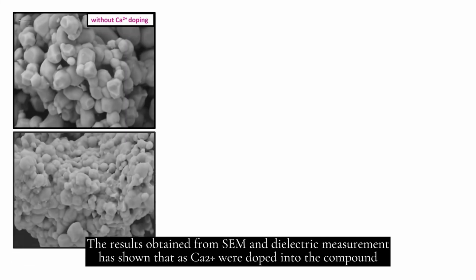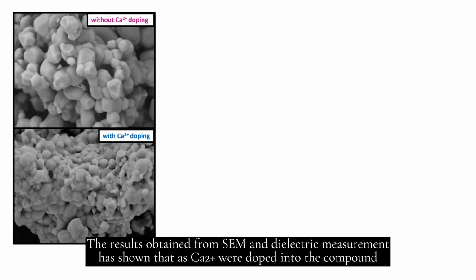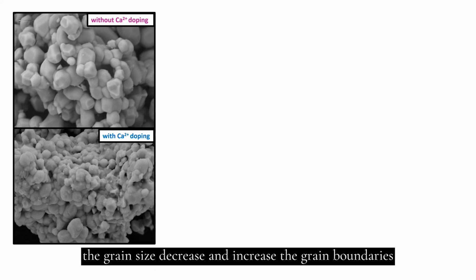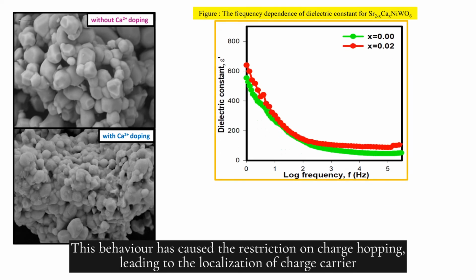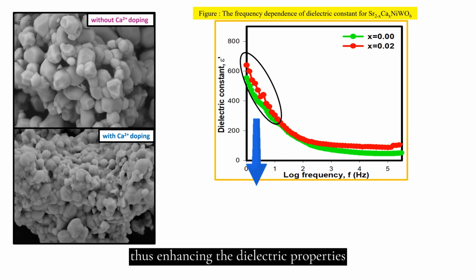The results obtained from SEM and dielectric measurement have shown that as Ca2+ was doped into the compound, the grain size decreased and the grain boundaries increased. This behavior has caused a restriction on charge hopping, leading to the localization of charge carriers, thus enhancing the dielectric properties.